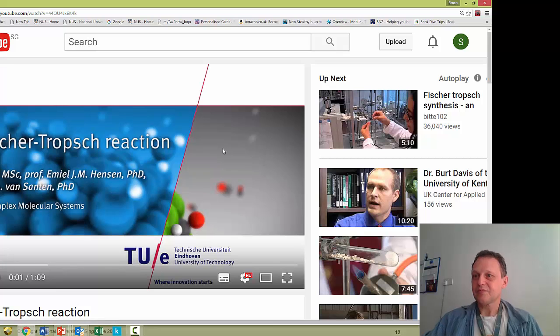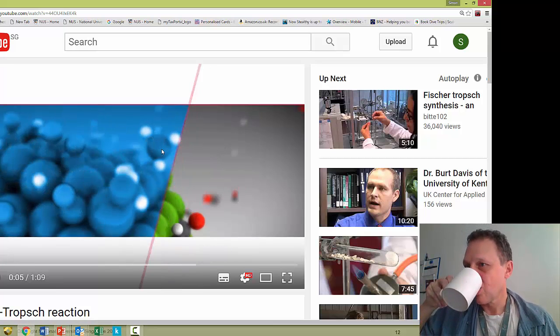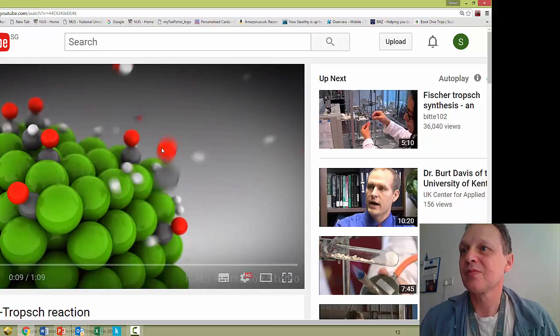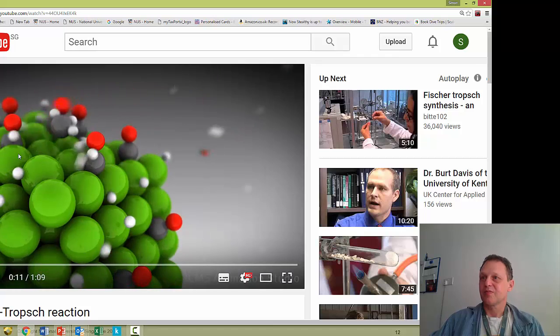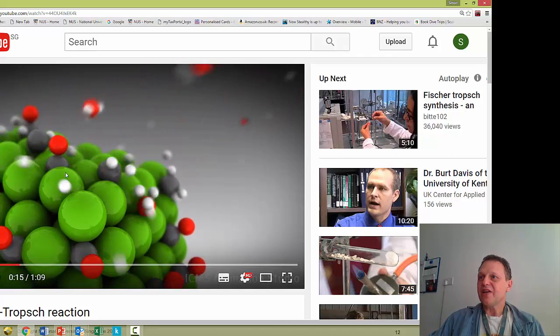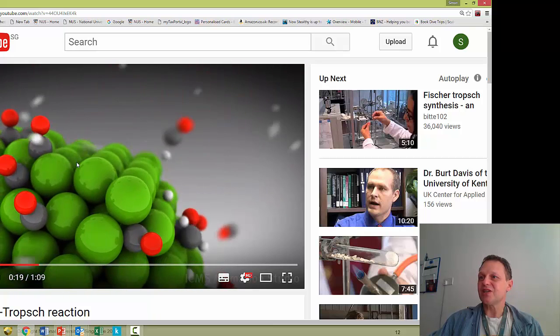This animation shows the fate of carbon atoms on different types of ruthenium nanoparticles. Dihydrogen decomposes rapidly. However, on a dense planar surface, carbon monoxide decomposes slowly into carbon and oxygen. Since there is a low concentration of free carbon atoms, methane and water are the only products.